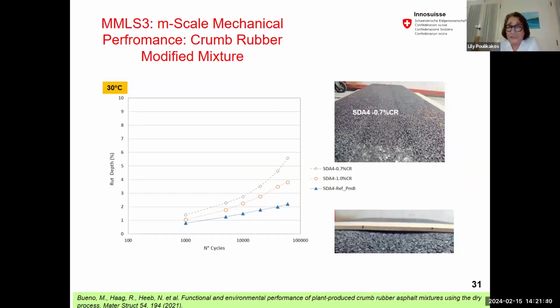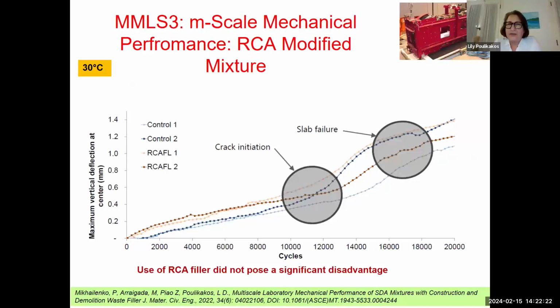And so here I'm showing you an example of the crumb rubber modified mixture. You see in blue, that's the polymer modified mixture, and these are the two with the rubber. So there is more rutting for the two crumb rubber modified mixtures. However, the maximum came to below 6%, and also the absolute value of the rutting was below what is normally considered acceptable. So for example, for other tests, 7 or 10% is something that is acceptable. Also, we did these large-scale tests for the recycled concrete aggregate modified mixtures. This is only the filler that was replaced. And so we don't see any significant disadvantage of using the RCA filler for our mixtures in comparison to the control.